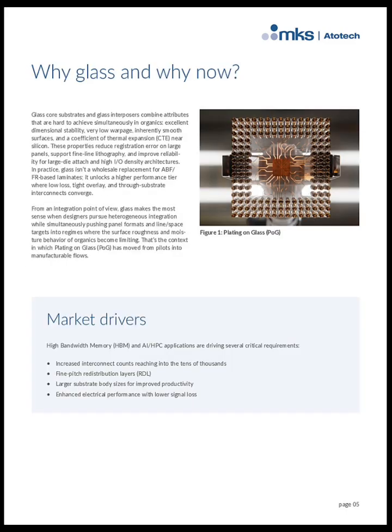So, why is glass gaining traction now? Glass substrates combine properties that are difficult to achieve with organic materials: excellent dimensional stability, low warpage, smooth surfaces, and tight registration. These enable fine-line lithography and higher interconnect densities, essential for modern electronics. Glass can replace traditional laminates, improving electrical performance and enabling through-substrate interconnects. Market demands like increased interconnect counts, fine pitch redistribution layers, larger substrate sizes, and reduced signal loss are driving this shift from pilot projects to manufacturable flows.